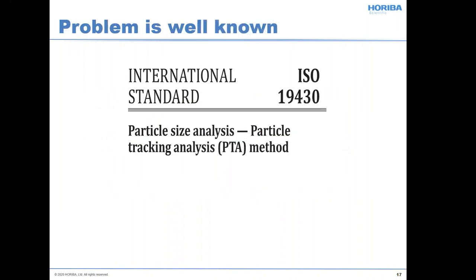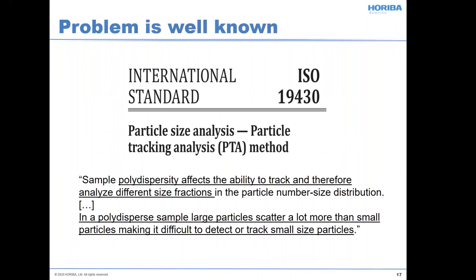This is a fairly well-known problem, addressed in ISO 19430. Polydispersity affects the ability to track and therefore analyze different size fractions, because large particles scatter more than small ones. The ISO committee is also working on updates to reflect the multi-laser approach.